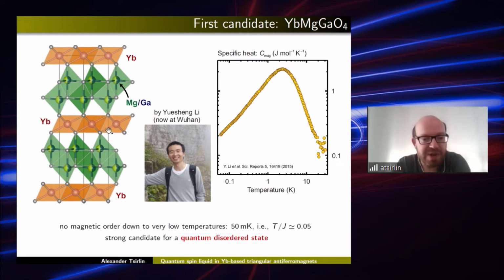It's actually a pretty simple crystal structure. We have ytterbium-3+ as the magnetic ion, and at low temperatures it can be described as an effective spin-1/2. So we have the strong quantum effects that we need to create a spin liquid. These are the triangular layers, and they're separated by slabs of magnesium and gallium, which are non-magnetic. So we have a very good separation between the magnetic layers, and we seem to have a suitable platform to create a spin liquid state.